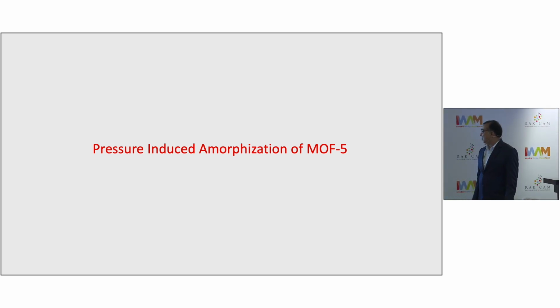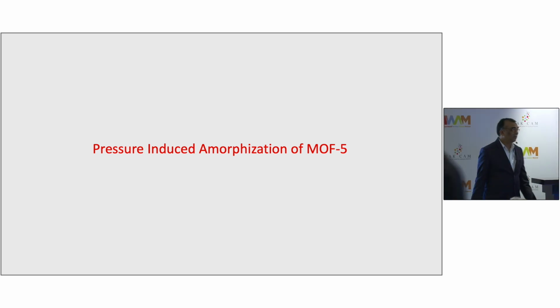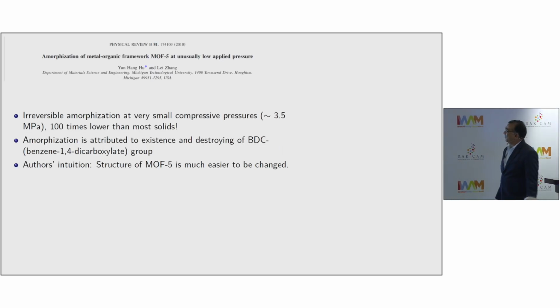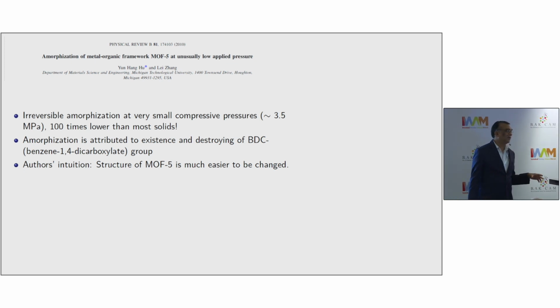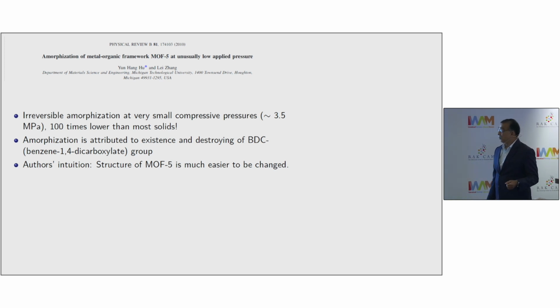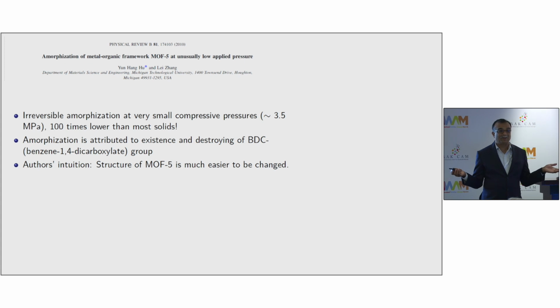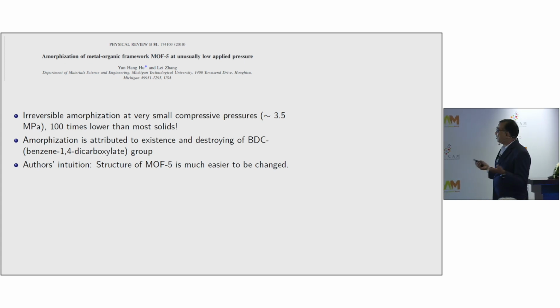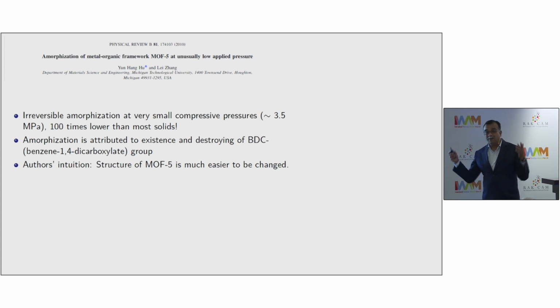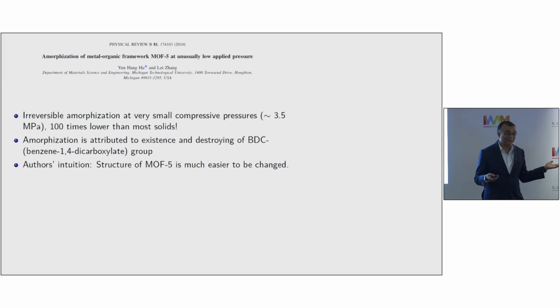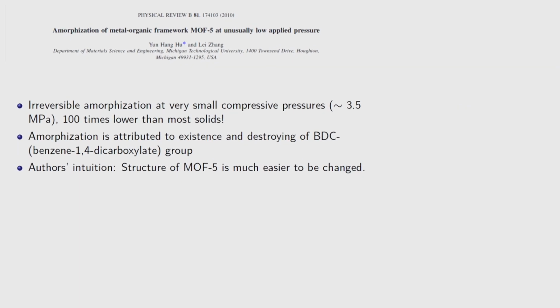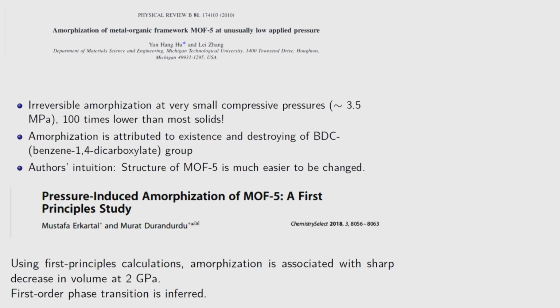So the second topic is amorphization of MOF5, which is again a very interesting problem. These crystals become amorphous at unusually small pressures, just a few hundred megapascal, which is 100 times lower than typical pressures required for amorphization of other systems. So the question is, and this is where we are going to say amorphization of a MOF is in competition with flexibility of a MOF in this case. So there was theoretical work as well a few years ago, which showed that there is a sharp change in volume at fairly low pressures, at 2 GPa, and a first order transition is inferred.